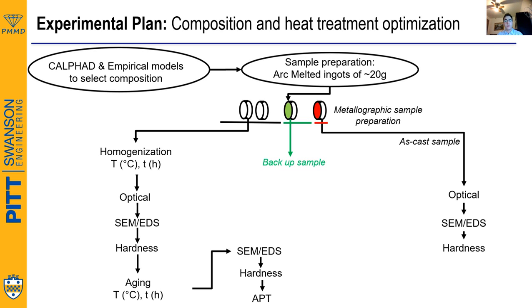Finally, using backscatter electron microscopy with energy dispersive X-ray spectroscopy, EDS, as well as atom probe tomography, we characterize the microstructure of the samples in their different heat-treated conditions. And lastly, we use Vickers hardness testing to quantify the mechanical properties of the sample.